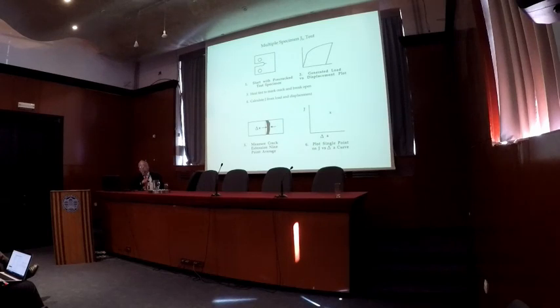So here is the multiple specimen technique. This is representing a fracture specimen. Load it into the nonlinear range where you assume to get ductile crack growth, and then unload it without breaking it. And then break it open, and we would take that specimen and put it in a very cold thing like liquid nitrogen, so it would be very brittle and break open brittlely. Before you do that, we would mark the crack extension by heating it.